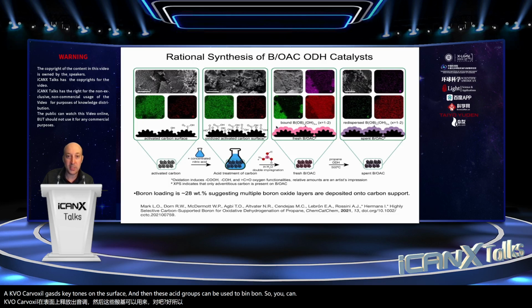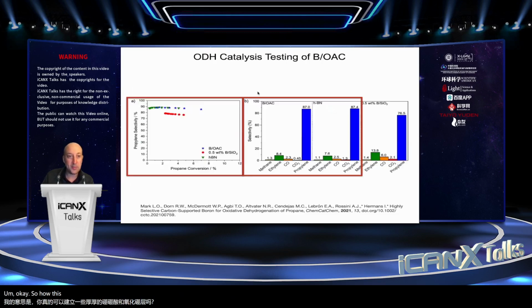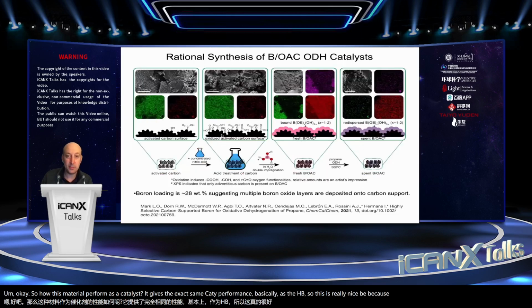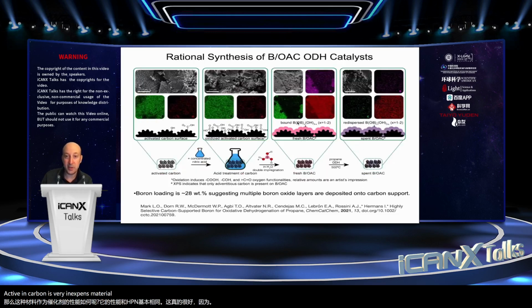And then these acid groups can be used to bind boron. So you can just take your carbon material, wash it with a boric acid solution, and you'll end up depositing this layer of boric acid or boron oxide on the surface of these carbon materials. And you can really build up some thick layers of this boric acid and boron oxide. Okay, so how does this material perform as a catalyst? It gives basically the exact same catalytic performance as the hBN. So this is really nice because activated carbon is a very inexpensive material, and boric acid is much cheaper, with much lower energy cost than something like boron nitride.